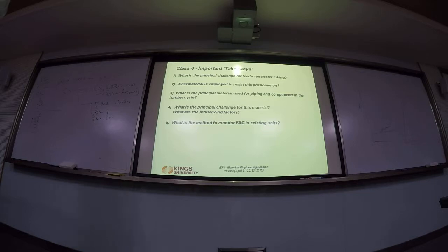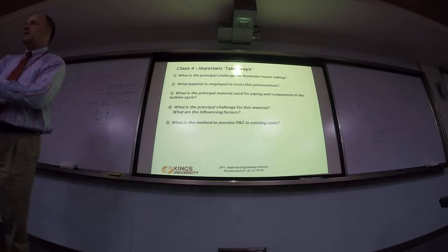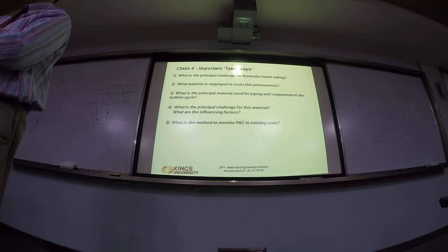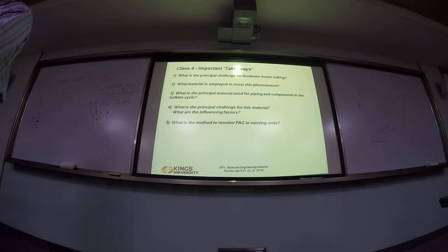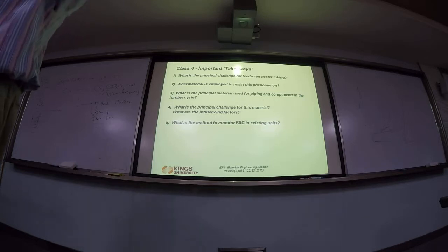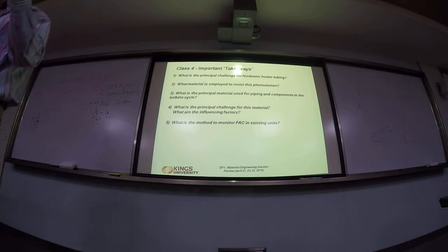So how do we see FAC with the grid system? Ultrasonic, right? We ultrasonically measure the FAC. How often? Every month? Every 6 months? Depends, right? If it's a high FAC, we might come back every year. Most FAC, we can come back every 2 years, every 4 years. But the thing about FAC is it's very uniform, a very constant rate. So there shouldn't be a surprise.